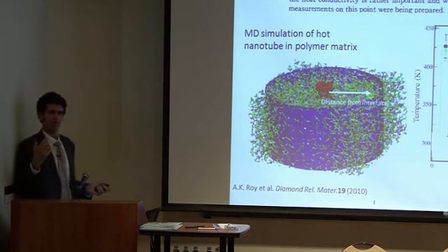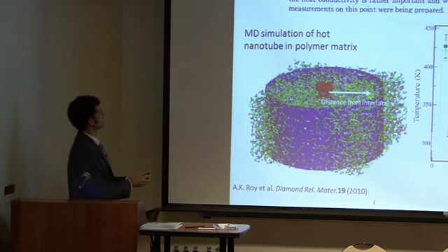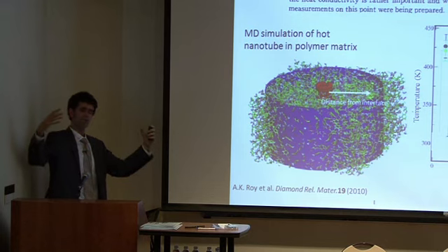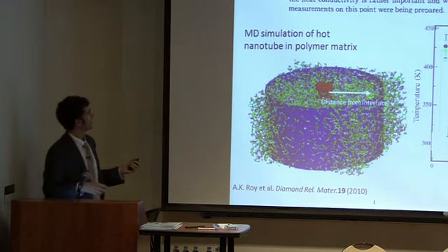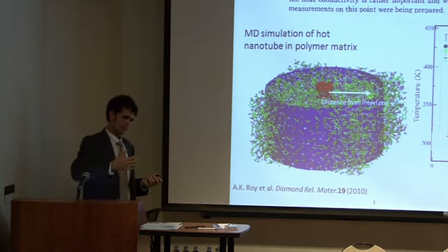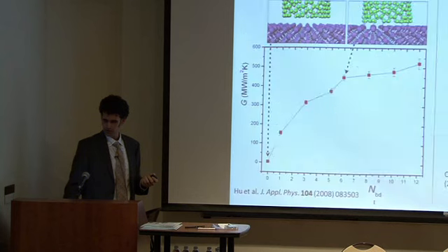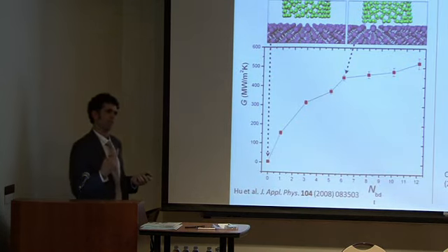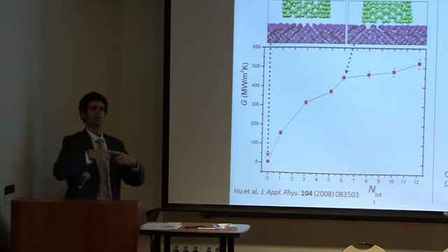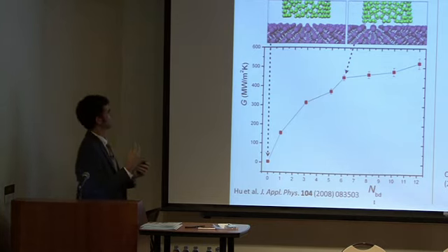The heat can't get out of this carbon nanotube. It flows superbly along the length of the carbon nanotube, but it doesn't go anywhere into this polymer matrix, which is really what you want it to do if you want to have homogeneous high thermal conductivity. And that's called thermal interface resistance, because there's an interface between the nanotube and the polymer, and it's like a barrier. It won't let the heat out. And there are 2 reasons that happens in these carbon nanotube-based composites, or even in carbon nanotube to carbon nanotube contacts. The same thing happens, and there are 2 reasons for it.